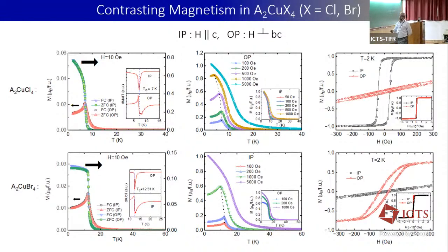But the important point is, in the chlorine case, if you look at the in-plane magnetization, it shows a ferromagnetic-like behavior. You expect 1 μB, here we are getting roughly 0.8 μB at application of a 10 Oe field. But if you do the measurement in the out-of-plane direction, you see there is a downfall. So you might wonder, could it be an antiferromagnetic transition? But it is not the case. As I go along, I'll tell you.